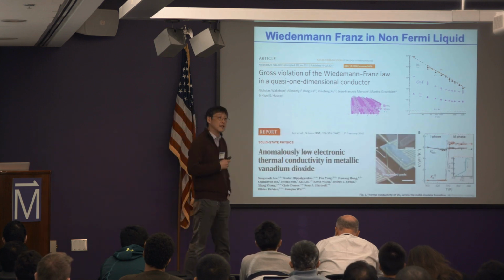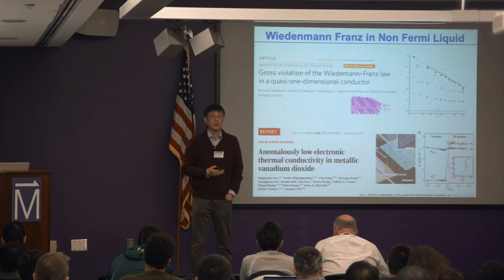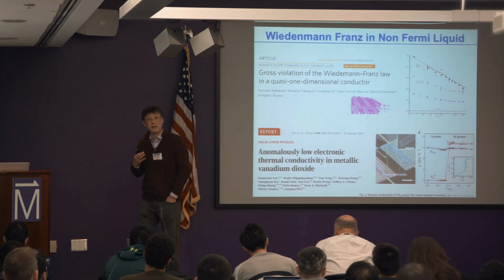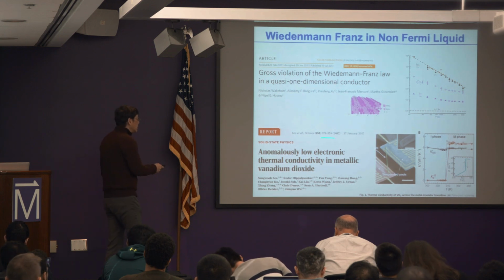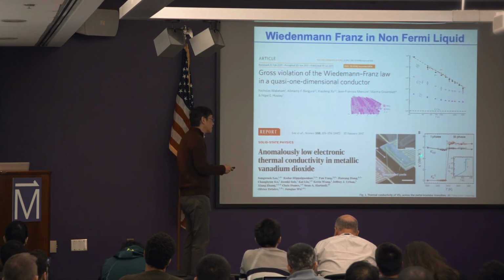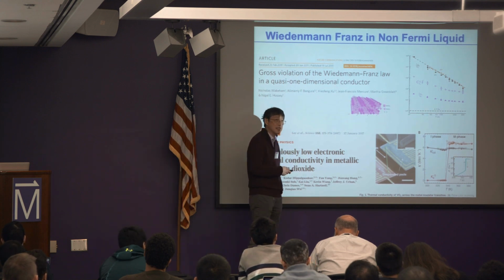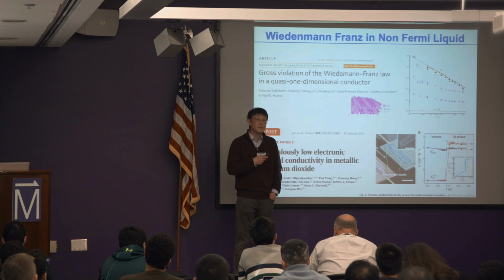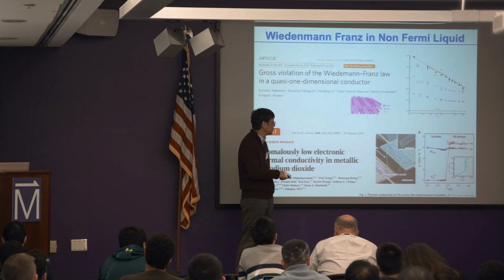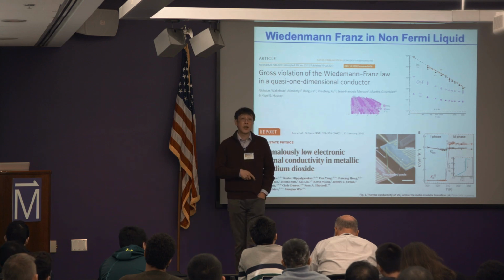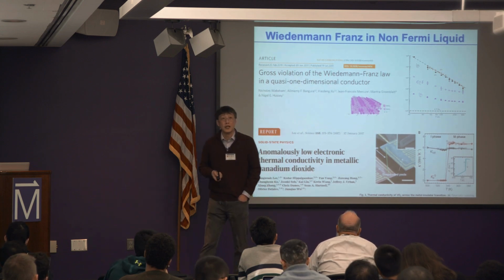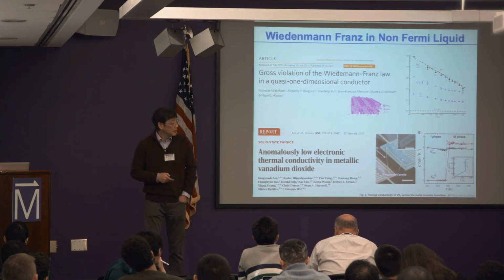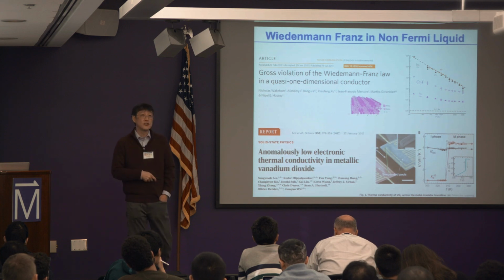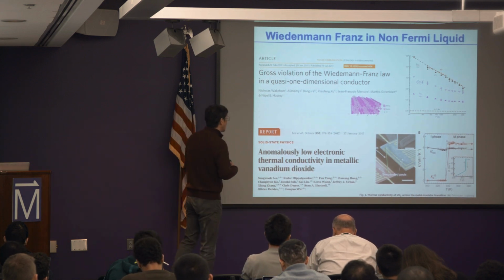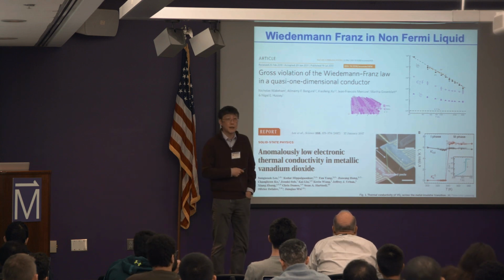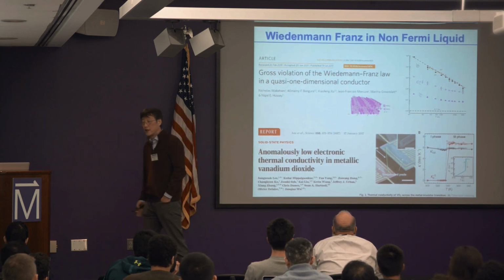Another example is vanadium oxide, which is a typical system where you expect to see metal insulator transitions happen. These folks actually measured the thermal conductivity and electrical conductivity of vanadium oxide nanowires. And they see that especially in the metallic regimes, very close to the metal insulator transition range, the Wiedemann-Franz law also breaks down quite severely, by about an order of magnitude, indicating that at least the electronic systems near these metal insulator transitions may not be described by this Fermi liquid. So there are some experiments out there that show the breakdown of the Wiedemann-Franz law.